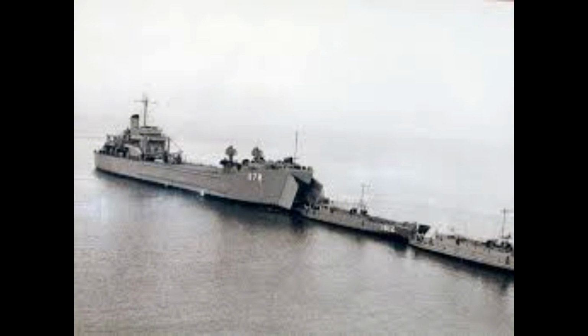The same pattern held across the invasion fleet. Of the 229 LSTs that participated in Sicily, 3 sustained hull damage severe enough to require shipyard repairs. None broke apart. None developed the kind of catastrophic fractures that were still plaguing Liberty ships. The welding procedures, so painfully developed over the previous year, had proven themselves under the only test that mattered.